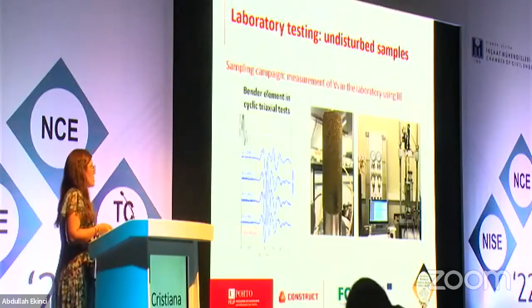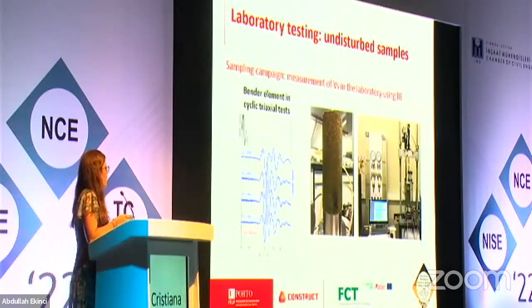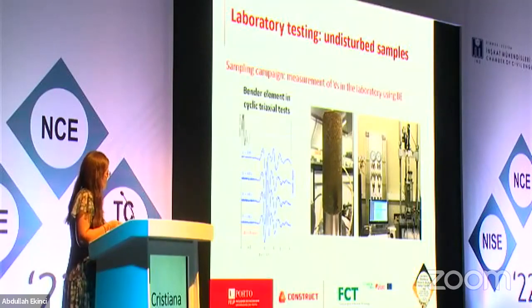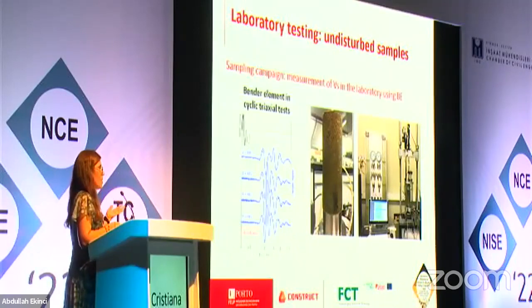And we also did the test with much more care and after reconstitution of the in situ stresses in the cyclic triaxial test and in any test that we did use samples. And you can see here an example of the measurement of the Bender elements using our procedure, which usually involves different frequencies, and we take the first arrival from the common point of the arrival of the shear wave.